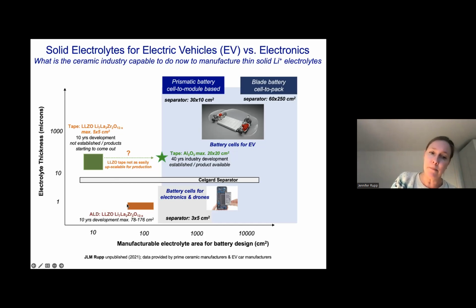There are some companies, like a very well-known Californian manufacturer that I won't name now, that, for instance, look more into vacuum techniques, right? And atomic layer deposition is definitely a very hot one here. That's similar to what I showed you before in pulsed laser deposition. So you're capable of making very thin films, which is great. But then the upscaling gets very expensive, and it's also hard to do because you're vacuum bound. So reaching 30 by 10 square centimeters, like 12 by 4 inches, is actually quite challenging.